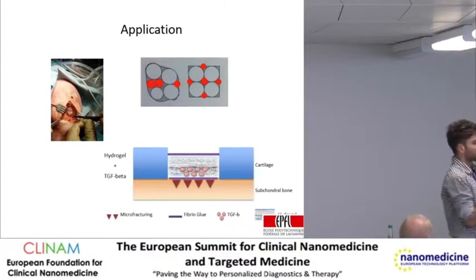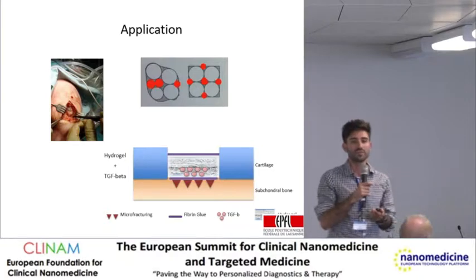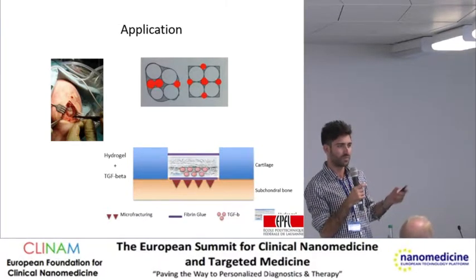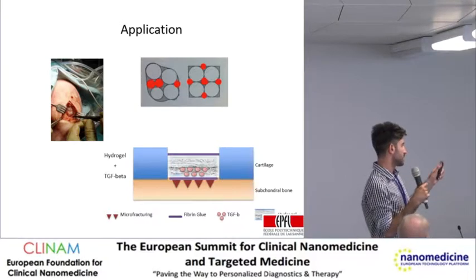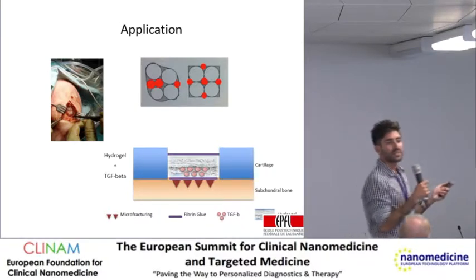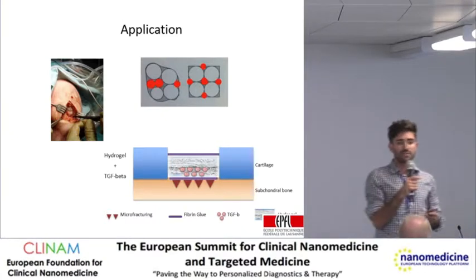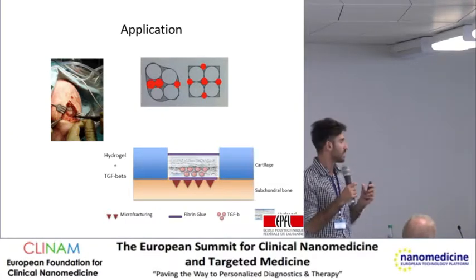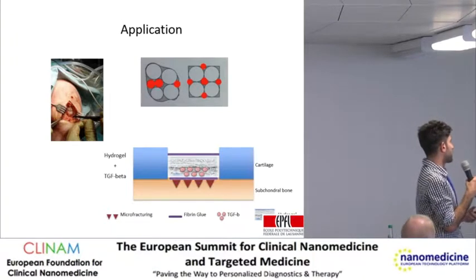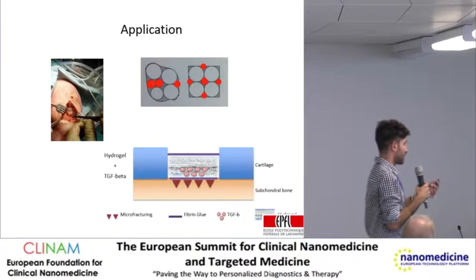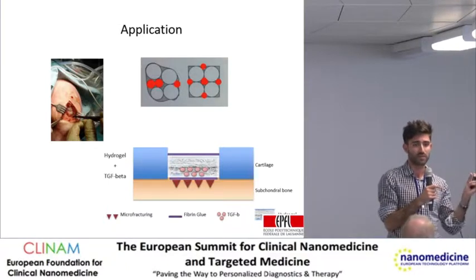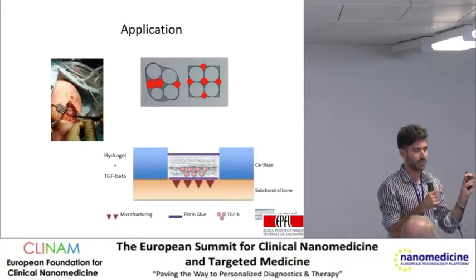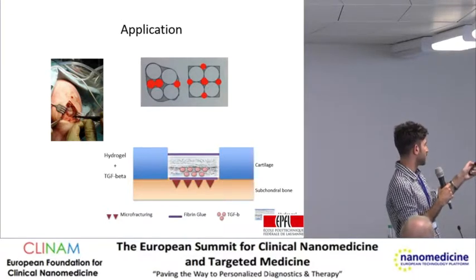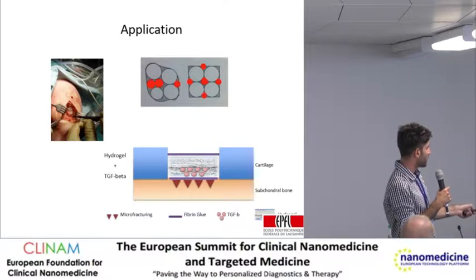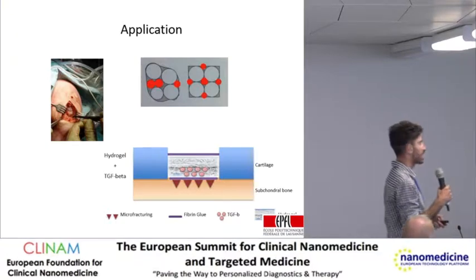For this hydrogel, the idea was that we didn't want to have interaction with drugs. So as you saw, we just played with the permeability of the gel. So basically any kind of drug can be used in this system. We just need to match the size of the drugs with the permeability of the gel. For example, one application is mosaicplasty in knee cartilage, when they move a plug of cartilage from the non-load bearing side to the load bearing side. These kinds of drug plugs can be used in between our cartilage plugs to release the required growth factor drug, and degrade after a while.